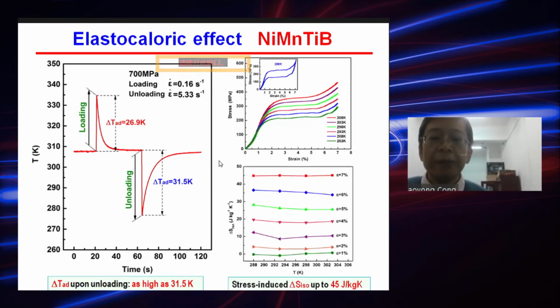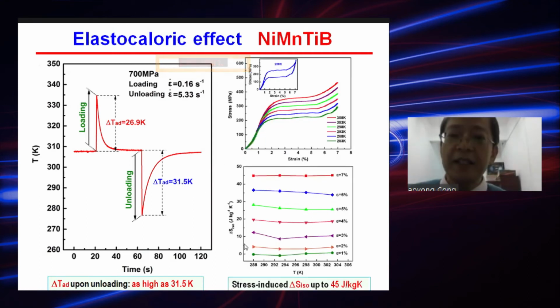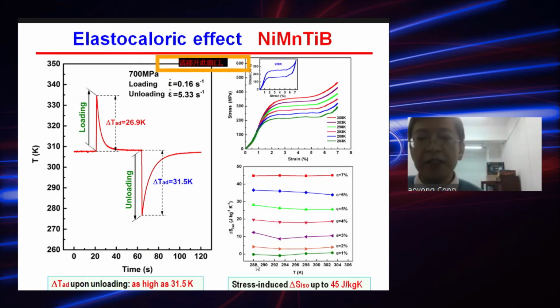When we tested the elastocaloric effect, surprisingly, we find that during unloading, we can get an adiabatic temperature change as high as 31.5 Kelvin. We also estimated the stress-induced isothermal entropy change by integrating the areas on the stress-strain curves measured at different temperatures. We find that the stress-induced isothermal entropy change is up to 45 joules per kilogram per Kelvin.